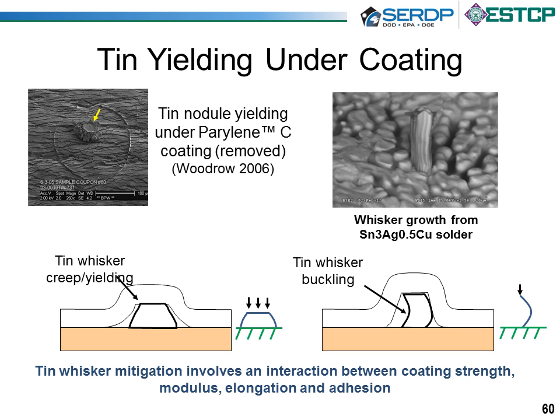And the interaction between the coating and the whisker is complex. We get tin growth growing up underneath the coating. As the coating stretches, it becomes stronger. We saw some of it strain hardening as the polymer segments align. The tin creeps and yields underneath the coating. So it has pretty poor creep resistance, which is good for us, but it's a metal, it's not a polymer. If the whisker gets long enough, we can take advantage of buckling, because once the buckling load is achieved, the whisker collapses pretty readily.